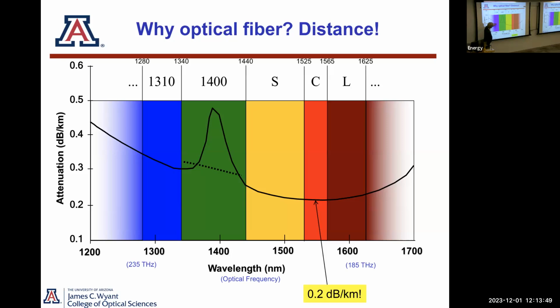You can see that for optical fiber, there's a minimum at about 1550 nanometers in the loss. The loss in this direction, this increase, is Rayleigh scattering, same thing that makes the sky blue. This big peak here is water. When you make silica, you always have a little bit of SiOH left over, and that SiOH, the OH, gives you this so-called water peak. You can get rid of it, but it's not really worth it usually.